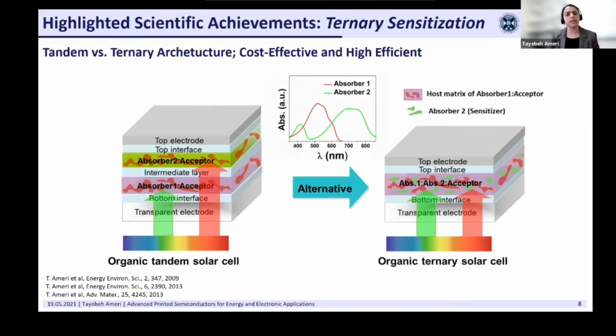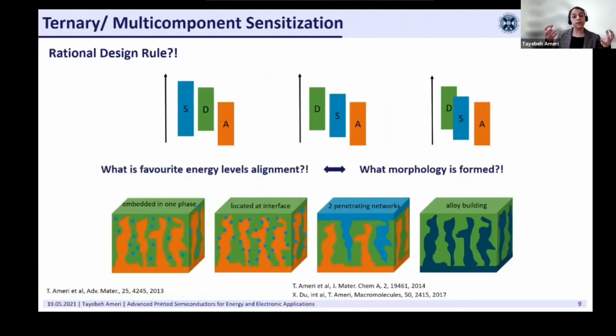And it was the time we started developing a new concept called Ternary Solar Cells, or also called Ternary Sensitization, where we introduced a second absorber or sensitizer with a complementary absorption profile to the host material, absorber 1 and acceptor. So now we are dealing with a blend of three materials in our photoactive layer, and for sure we should understand what is the favorite energy level alignment between these three materials and how it responds to the morphology formation and the device performance.